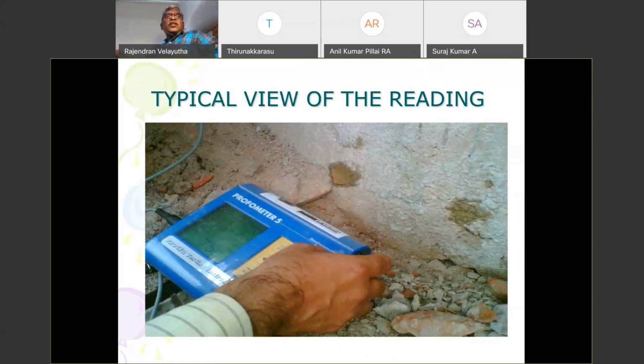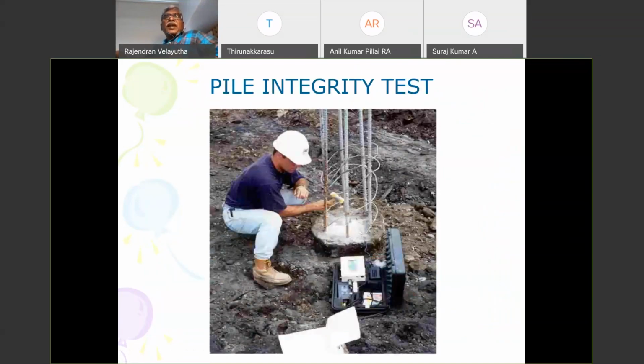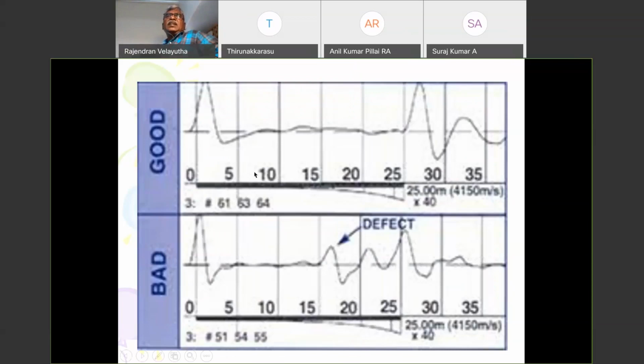At this place, it gives you 75 millimeter as the diameter and thickness of the cover. And the last one is a pile integrity test. What we do is we keep an accelerometer. It's called a pickup or otherwise, and you're going to have an instrumented hammer. You're going to hit it 6 times, at 6 places all around this, and then you do the test. It gives you a figure from which the depth of the pile can be calculated, and whether any neck formation, or any bulging has taken place in this pile.